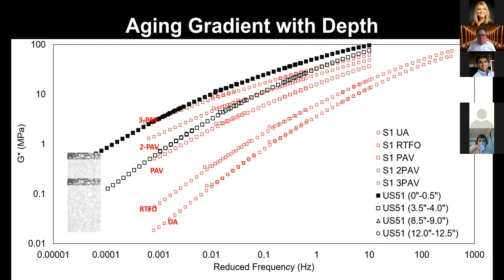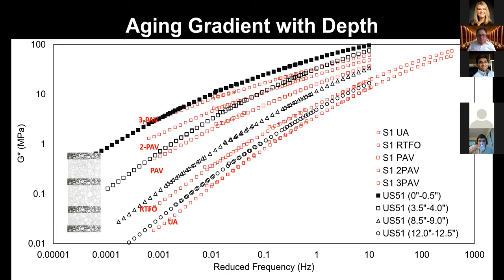Further down into the core at 3.5 to 4 inches matches more closely with this double PAV at the higher frequencies. As you move further down into the core, 8.5 to 9 inches, we see that that's between RTFO aged and single PAV. And then when we get to the very bottom of the core, between 12 and 12.5 inches, you will see that it's not quite the same as the unaged binder, but not quite the same as much as RTFO aged. So this tells us a significant amount about where we should perhaps set these aging parameters for